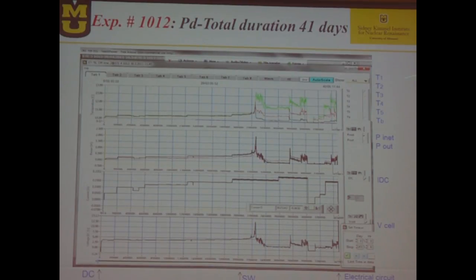And so, no excess heat. Actually, you see, the calibration was such that even P out was lower than P in. So we had what is called negative COP. And it was like this until the moment where we moved to superwave. After a few hours after moving to superwave, suddenly you saw the burst and the temperature increased, and we got excess power gain of 70%, and we had a few such experiments.